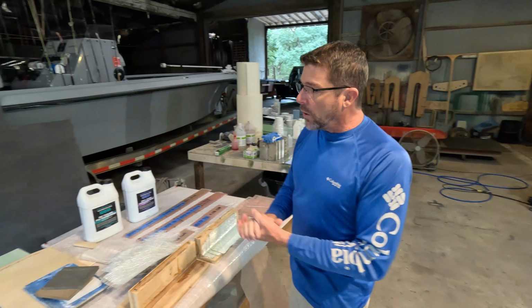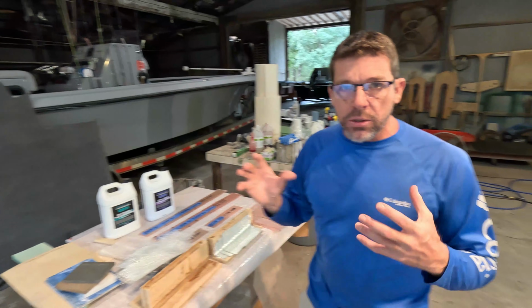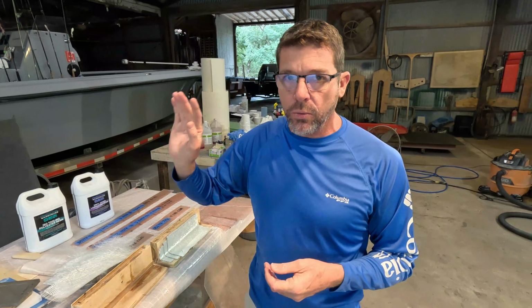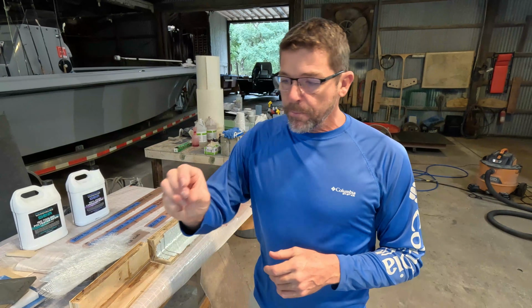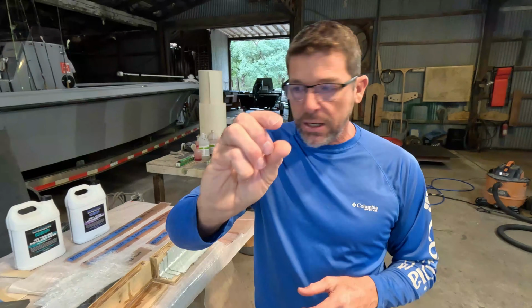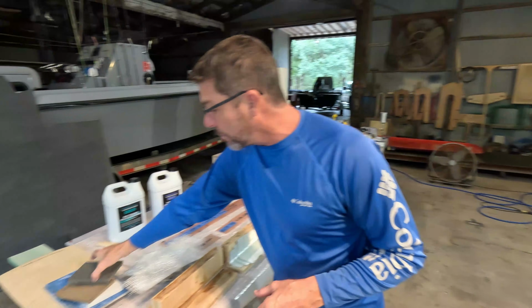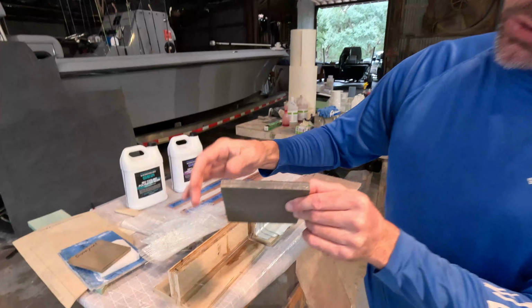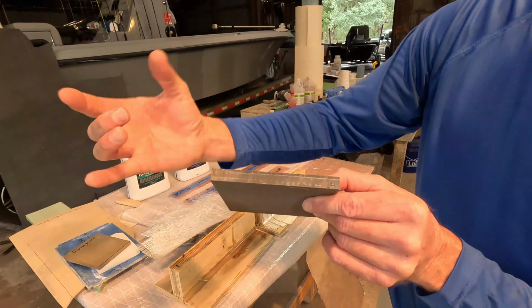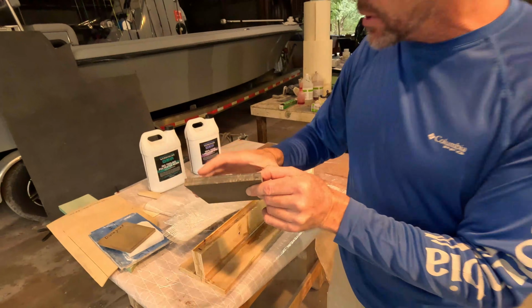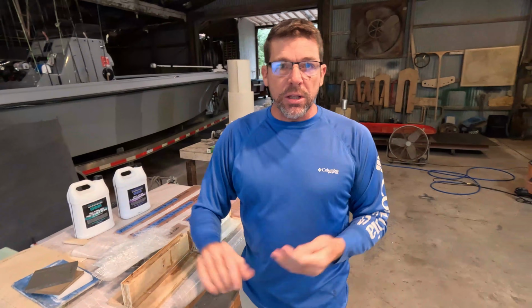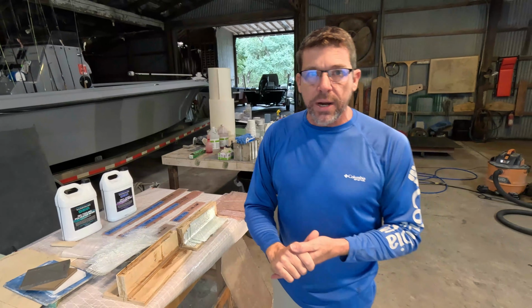For example, on our 29, we are mostly fishing offshore, and that boat will run nearly 50 miles an hour. So for a boat that size, we have right at 1/2 inch of fiberglass laminate. To put it at scale, that piece of Coosa is right at 1/2 inch thick. So there is right at that much fiberglass just on the bottom. And then you see how heavy duty the transom is.